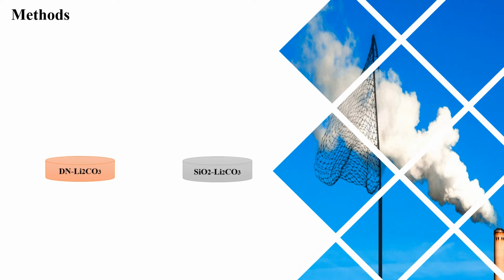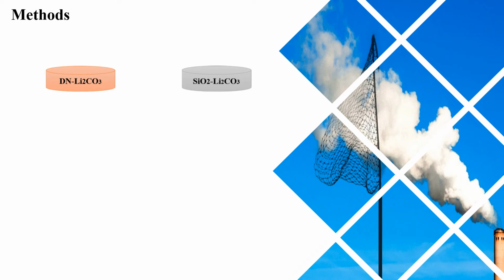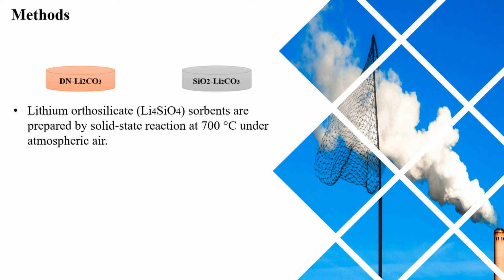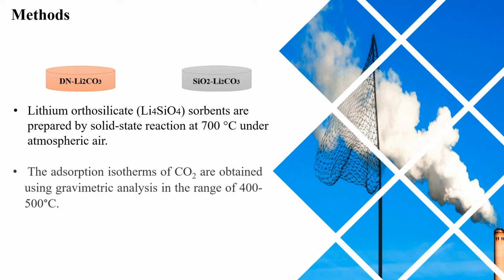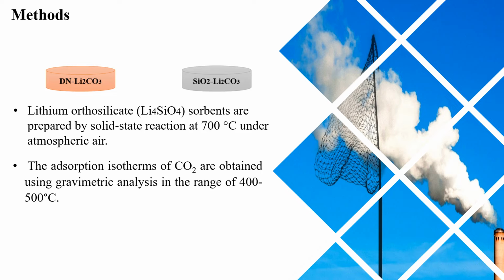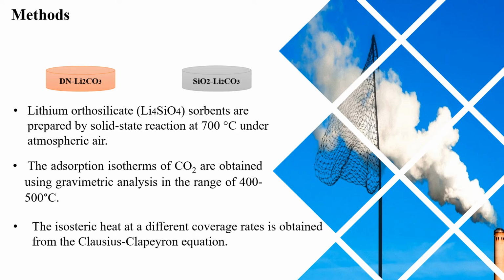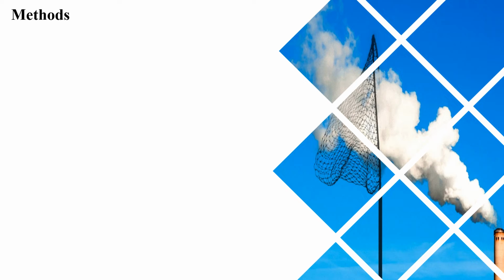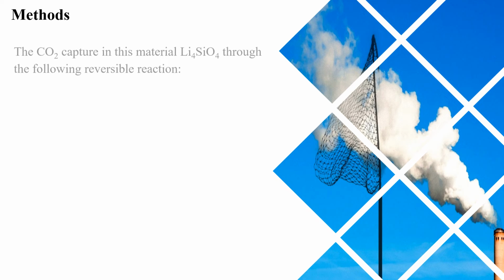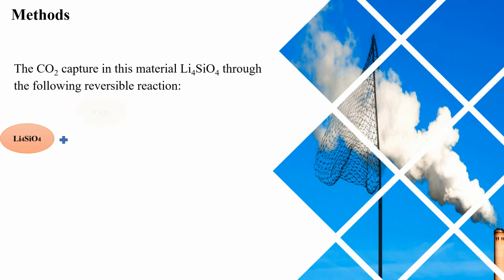Lithium silicate sorbents are prepared by solid-state reaction at 700 degrees Celsius under atmospheric air. Adsorption isotherms of CO2 are obtained using gravimetric analysis in the range of 400 to 500 degrees Celsius. The isosteric heat at different coverage rates is obtained from the Clausius-Clapeyron equation. The reaction between CO2 and our lithium silicate adsorbent follows the following reversible reaction.